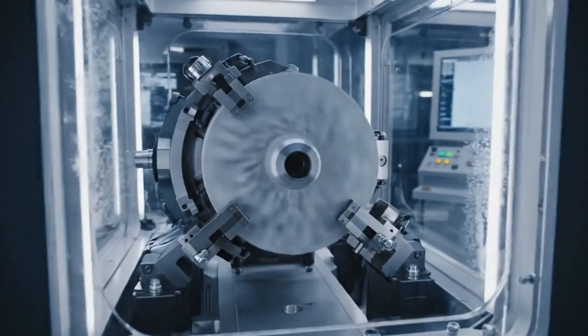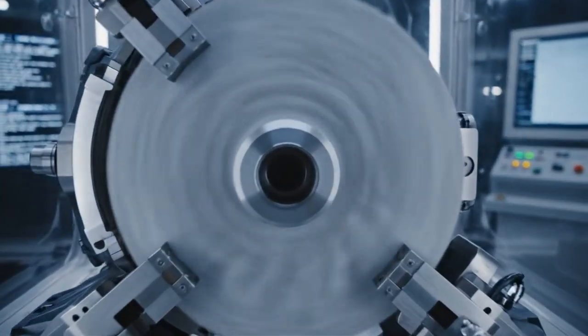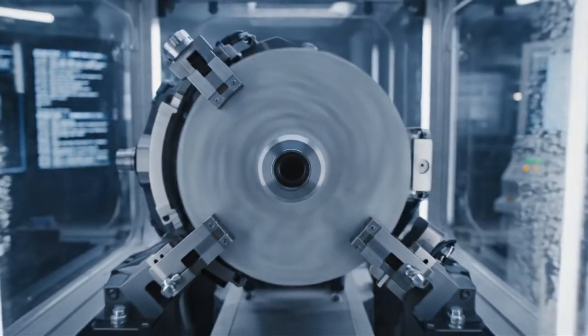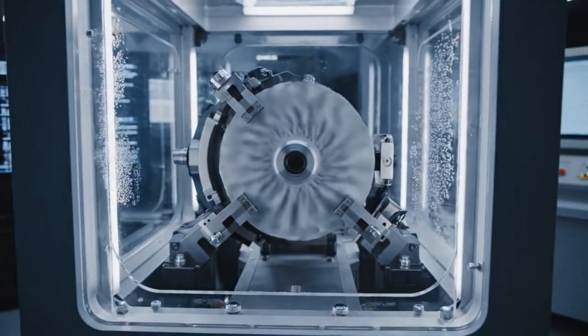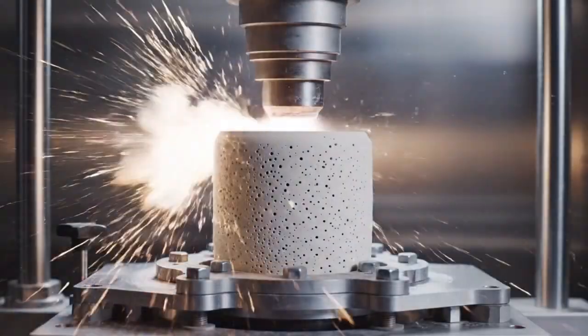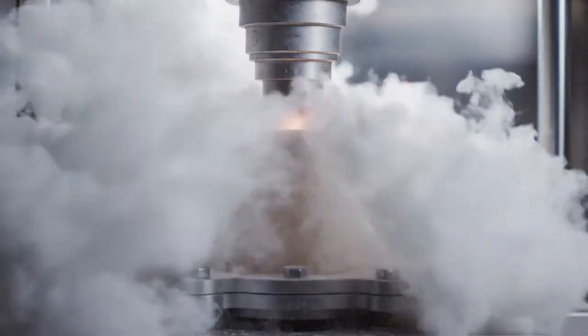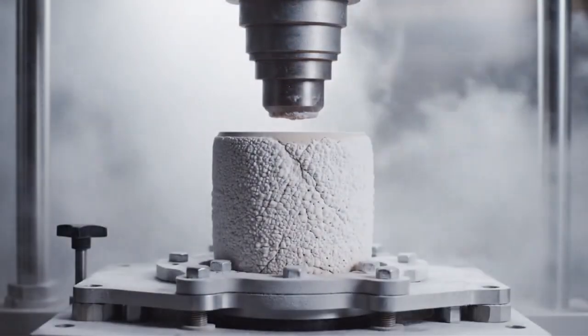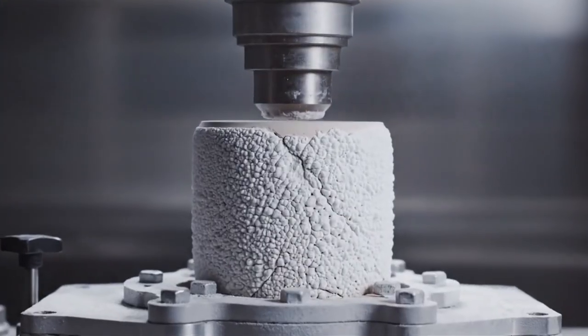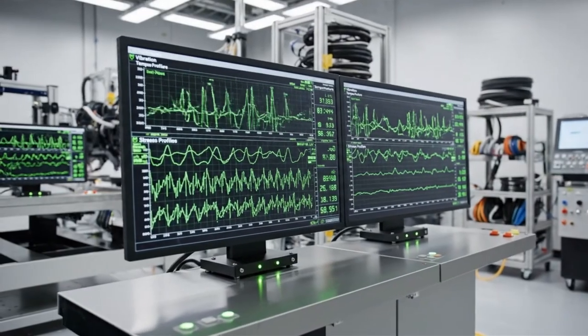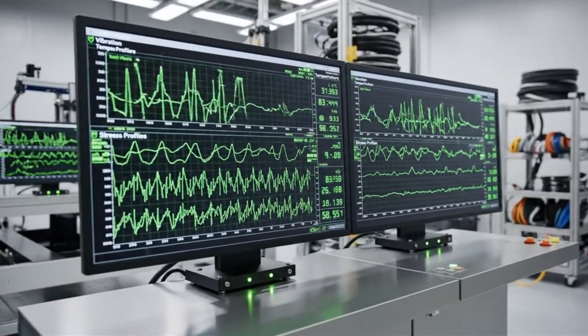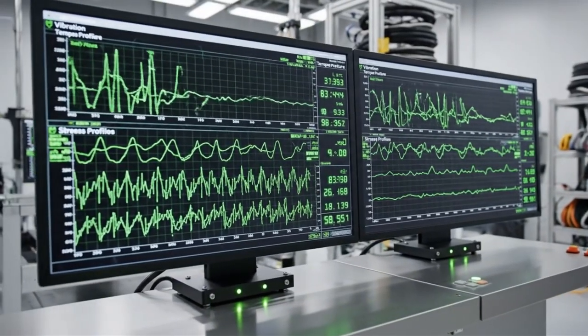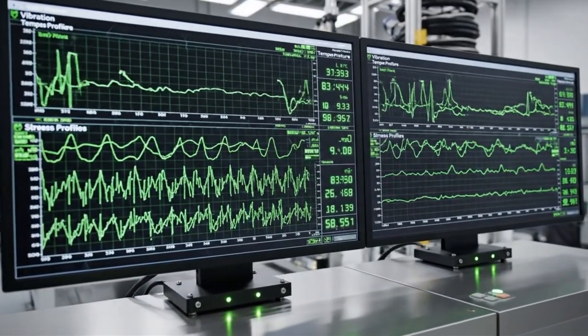The ceramic component has reached 40,000 RPM, showing minimal deflection within the pressurized chamber. A sudden blast of cryogenic vapor simulates extreme thermal shock, immediately freezing the ceramic surface. All systems are nominal. Vibration, temperature, and stress profiles remain well within acceptable parameters.